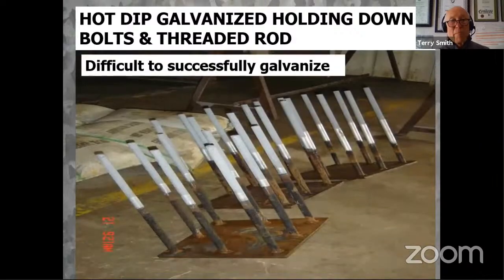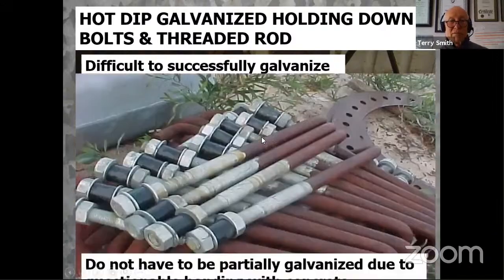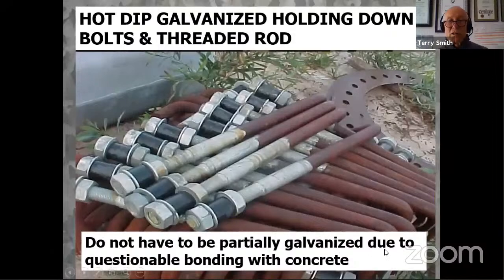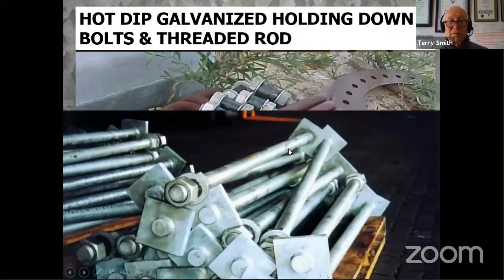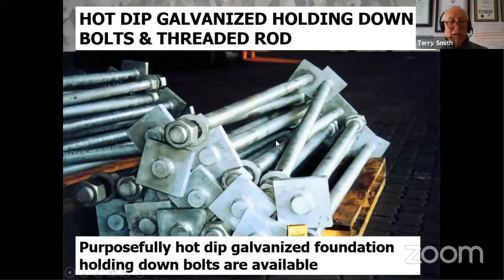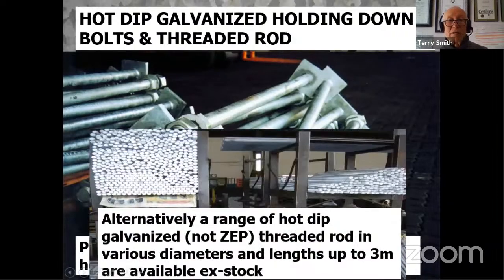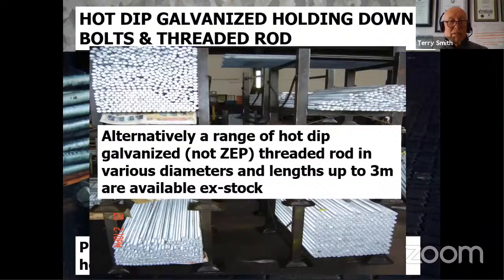Threaded rod or holding down bolts are difficult to successfully galvanize. You can see these being galvanized, but they have to be cleaned off with wire brushes, etc., and not always the most successful. They don't have to be partially hot dip galvanized due to questionable bonding with the concrete. As Martin talked about, there's no change. In fact, there's better bonding if the whole thing was hot dip galvanized. You can see purposely hot dip galvanized foundation bolts are available, and alternatively a range of hot dip galvanized threaded rod in various diameters up to 3 meters are available ex stock.